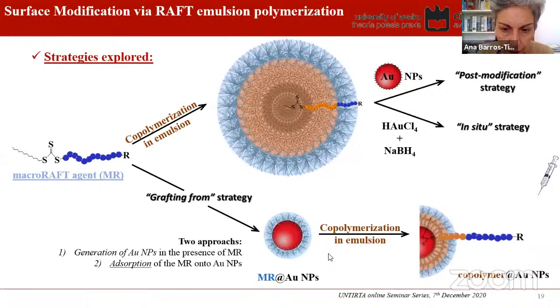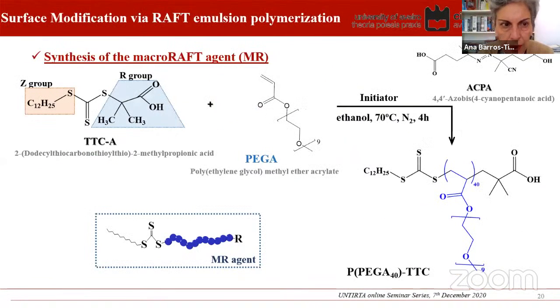As an alternative, we also looked into the grafting from strategy, but again, in this case, we considered two approaches. One, the generation of the gold nanoparticles in the presence of the macro RAFT, and two, the adsorption of the macro RAFT onto the gold nanoparticles, followed by emulsion polymerization. Basically, the chain extension was carried out in emulsion conditions.